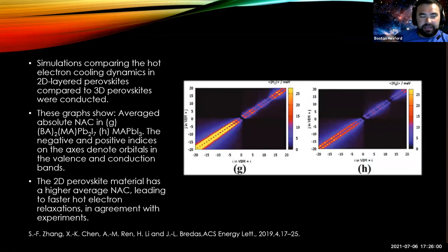So where was I? Some simulations comparing the 2D perovskites to 3D perovskites were conducted, and so these graphs show the nonadiabatic couplings in the 2D perovskite and the 3D perovskite, and the 2D perovskite has a higher average nonadiabatic coupling, which means the charges will recombine faster.